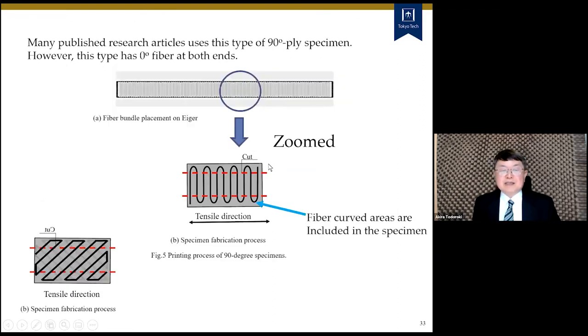And please be careful. You can find many published research articles in the many journals, and they usually use this type of 90-degree print specimens, but this is magnified, zoomed. In the Markforged slicer software Eiger, even in the 90-degree specimens, these fiber curved areas are included in the specimens. So this has 0 degree fibers around here.